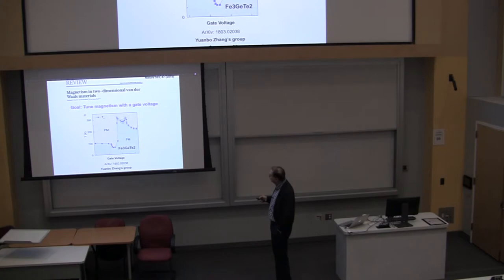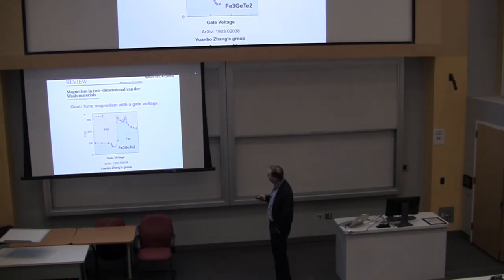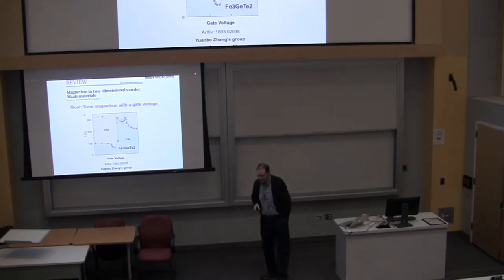So this is the iron 3 germanium tellurium 2 system. This is a 2D itinerant ferromagnet. So they cleaved it down. I believe they used ionic liquid gating, and they were able to control the magnetism to some extent. Last time I checked, about a month ago, it hasn't been published. It's been on the archive for 6 months or something.